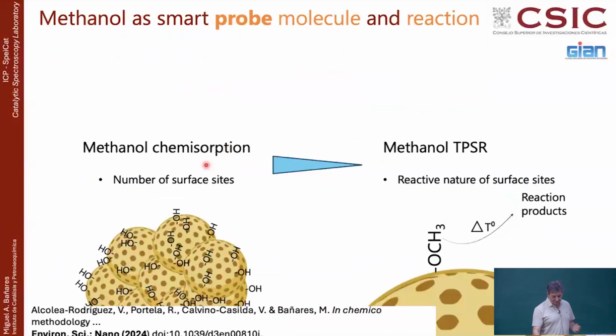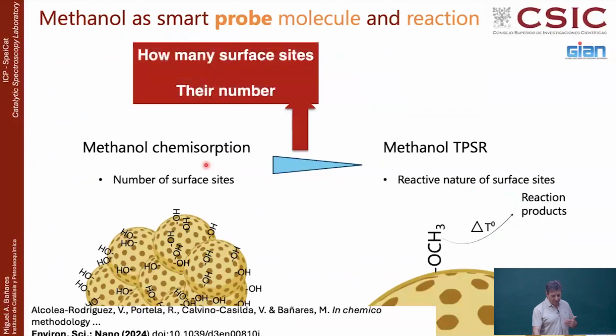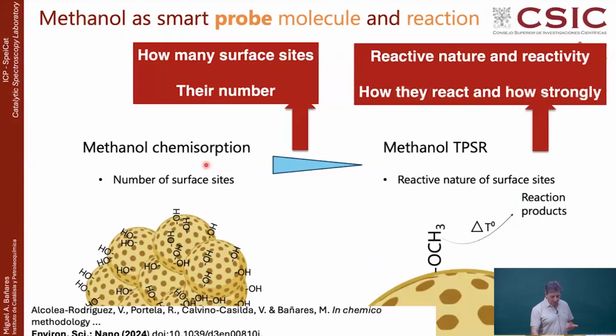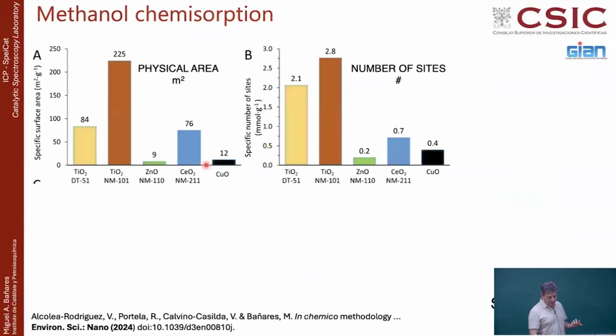Is it so? Well, we made the methanol chemisorption and TPSR of all these materials that the European projects on toxicity are doing. So with how many sites there are, the reactivity, and so on. And then we were ranking these materials. They typically rank the materials by area. So titania, high area, they have 200 square meters per gram. Okay. But the number of sites, of course, is very high. This more or less goes in parallel.